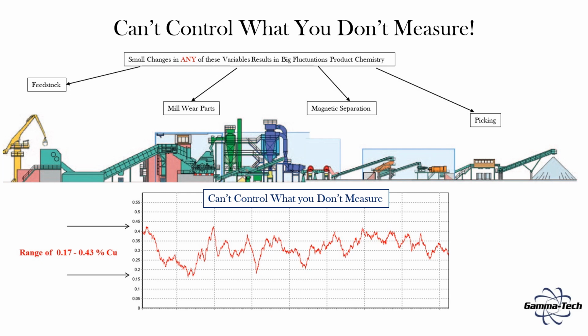We won't get into the details of shredding either, but there are several key components in the process that have a substantial effect on the quality of shredded produced. Again, particularly looking at the copper level, since it's of key interest to steel makers. The feedstock, as we've talked about, with its high variability and increased copper concentration, the shredding mill itself, how dense the product is exiting the mill, magnetic separation, air drops, and last but not least is the picking